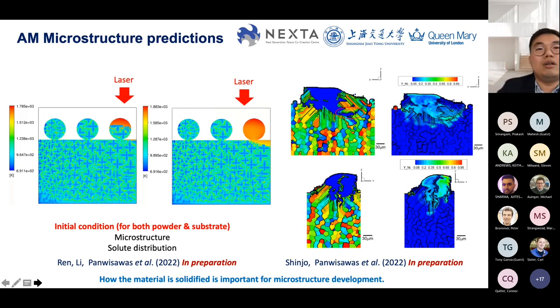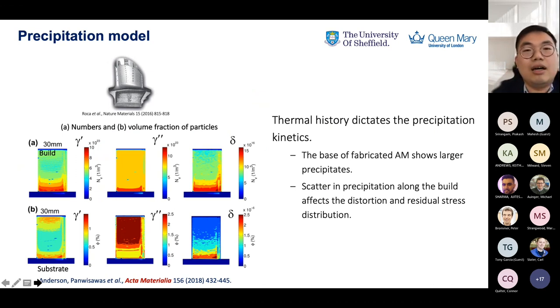Having said that, the thing we are going to do next is with regards to the precipitation model. I mean, as you know, there's some concern that the phase which is actually present in the printing is not as anticipated, because once you want to fabricate a nickel-based superalloy with high volume fraction gamma prime, you hardly see the gamma prime at the as-fabricated state. That is because of the very non-equilibrium nature. And once you do some post-treatment, this will start coming up. And then how can we understand and maximize the use of the model in order to give some direction for the post-treatment?